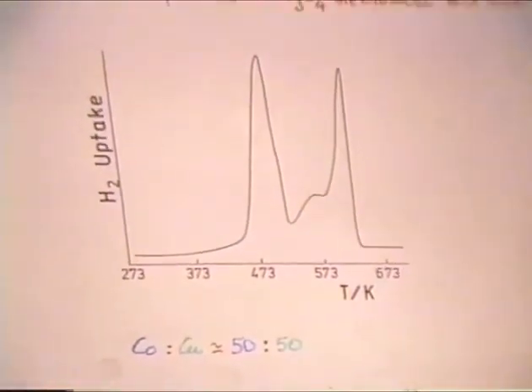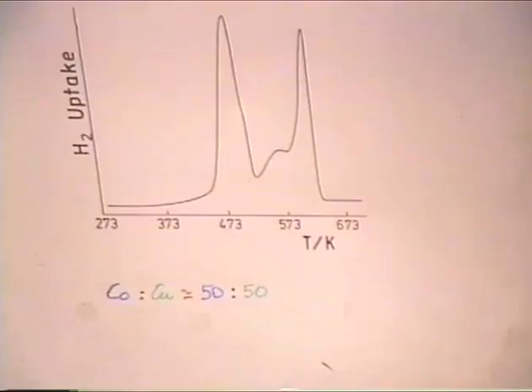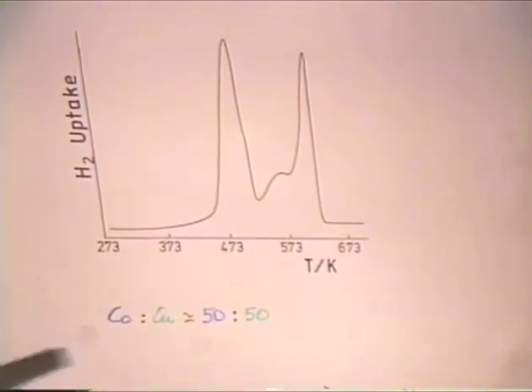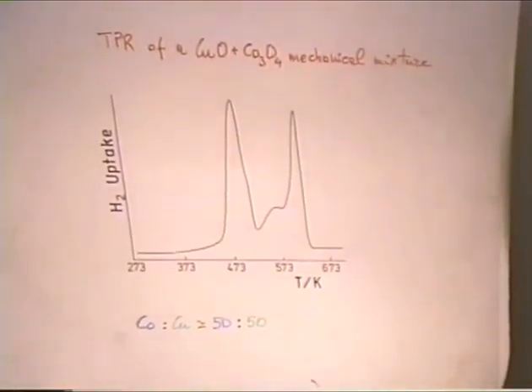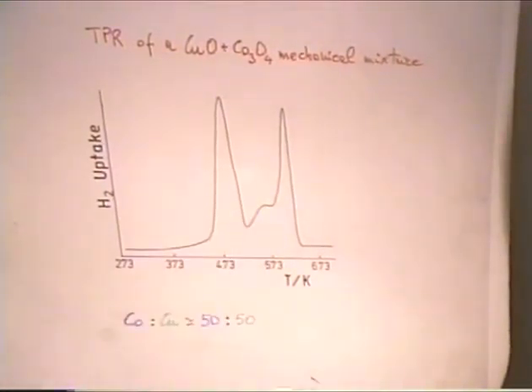of pure copper oxide and Co3O4 oxide, sorry. And the results of the TPR measurements on a mechanical mixture having a cobalt-copper composition almost equal to 50-50 are reported in this transparency. As you can see, the reduction profile of the mechanical mixture almost resembles that of the pure copper oxide and Co3O4. So this is a strong proof that in the cobalt-copper mixed oxide catalyst, the interaction is related to the preparation method and to the decomposition of homogeneous precursors.